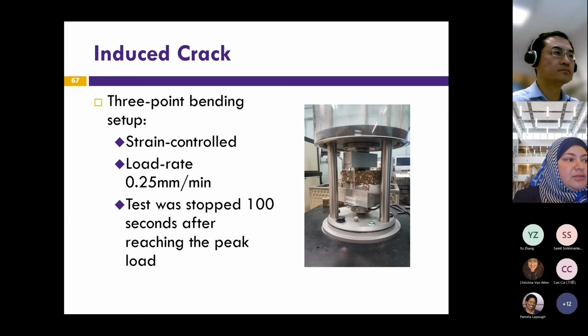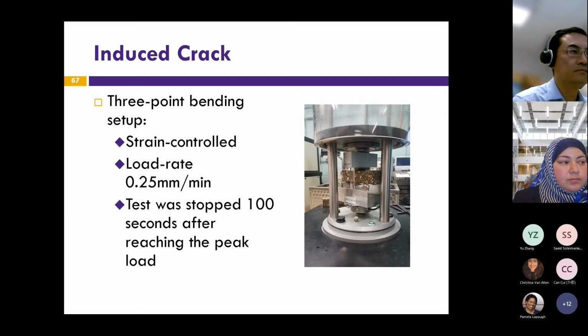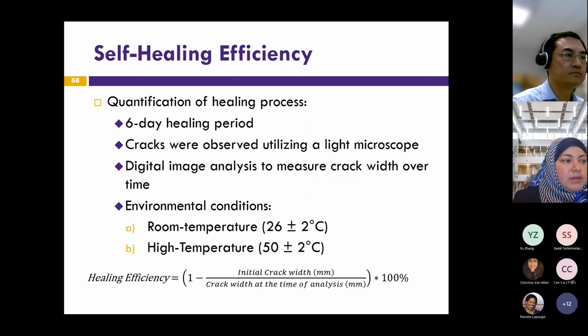So you can see here, that's the 3-point bending test setup. And we measured the healing process after 6 days. We left the specimens at room temperature and at high temperature. And we looked at the cracks using a light microscope after 1 day, 3 days, 6 days. We calculated the healing efficiency according to this equation.